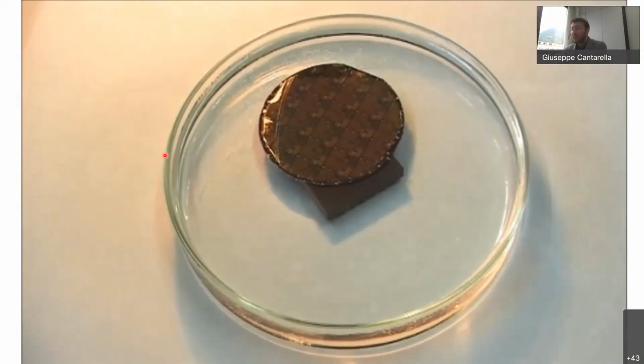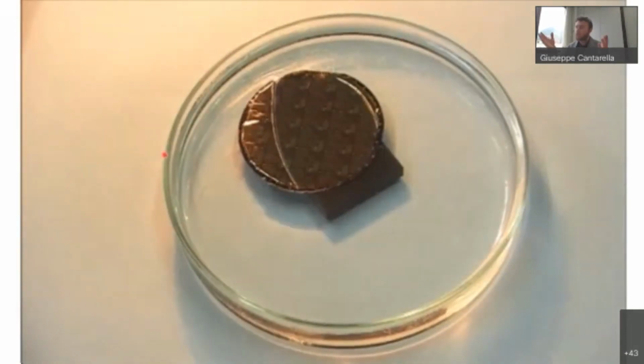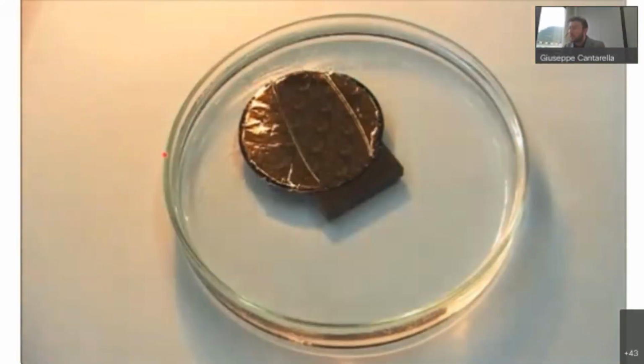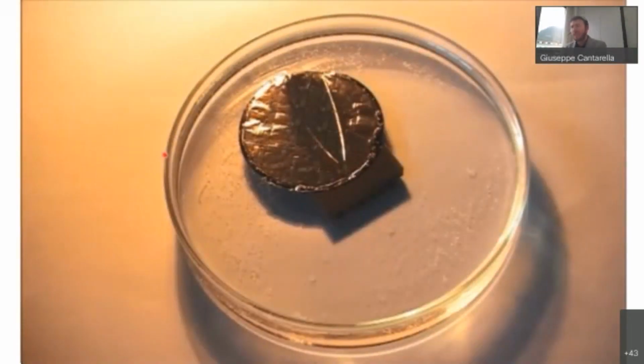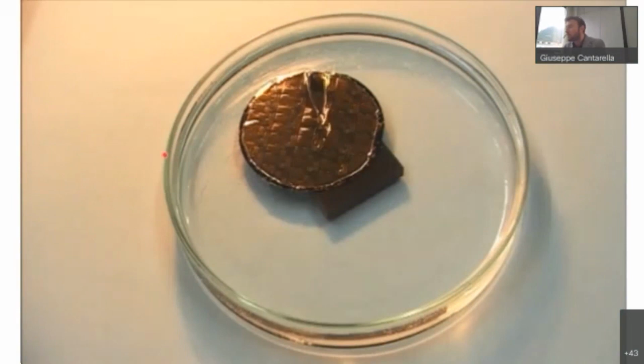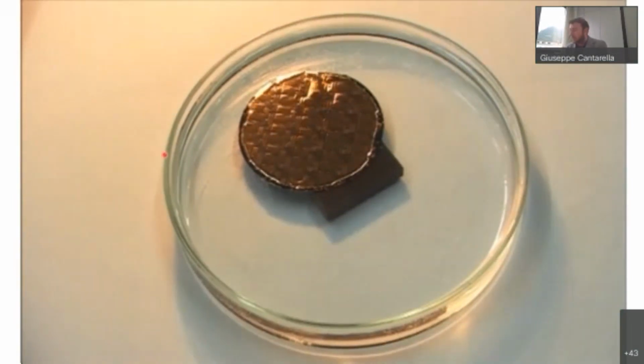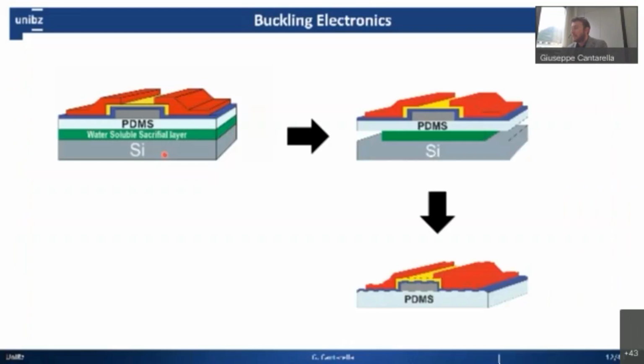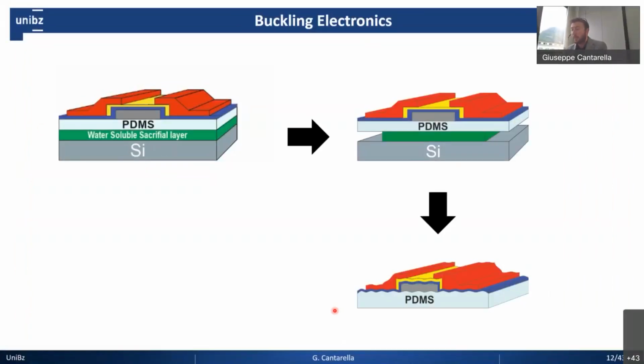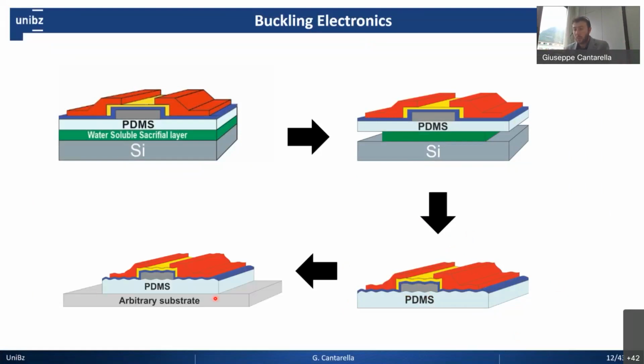In fast forward, what you see is the water going underneath and slowly dissolving the sacrificial layer. At the end, the result is a floating substrate with the electronics on top. The advantage is that after the dissolution, the elastomeric substrate releases all the thermal stress, so it shrinks, creating these out-of-plane wrinkles that I was presenting before. And then we can fish and place this elastomeric substrate on any arbitrary substrate.